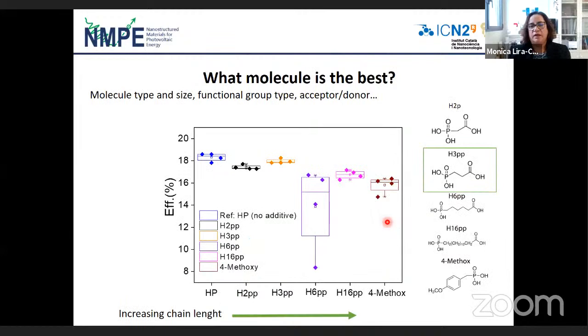Now, if you remember all the molecules that we use, it's not easy to say okay, if you use this molecule you will be able to obtain this result, because we believe there's also an effect of size. You can see here that we did start the calculation of the size and how they interact with the halide perovskite, and the one with the best matching in sizes is this molecule, exactly the one that we obtained.